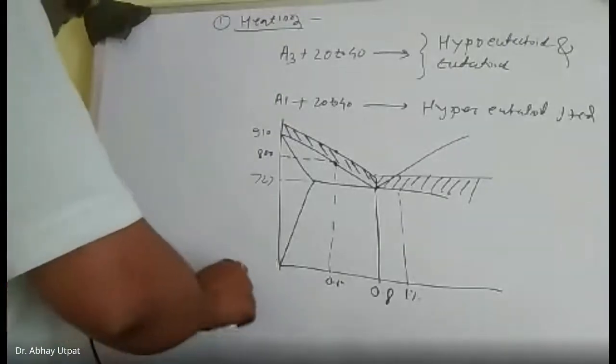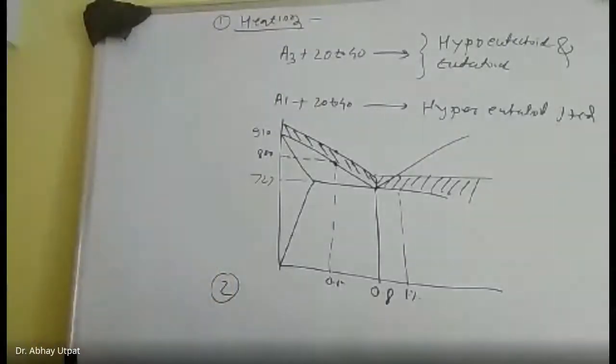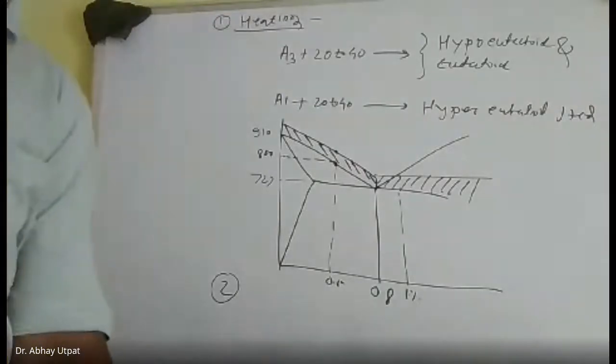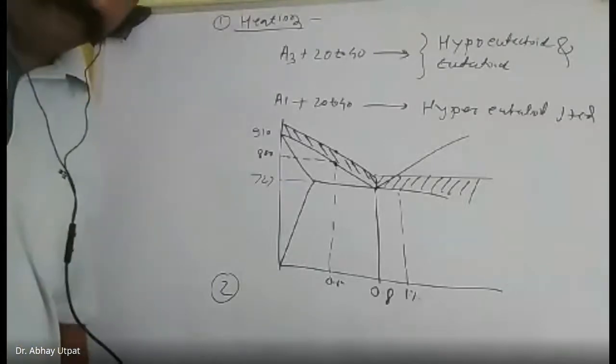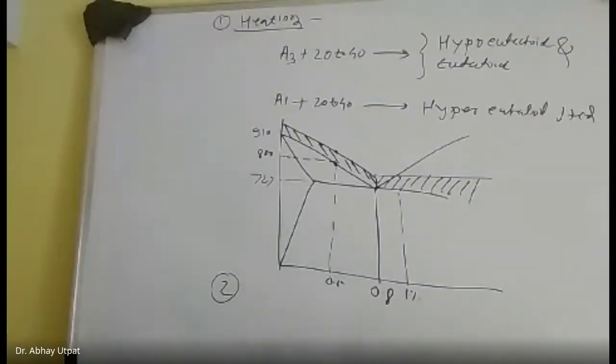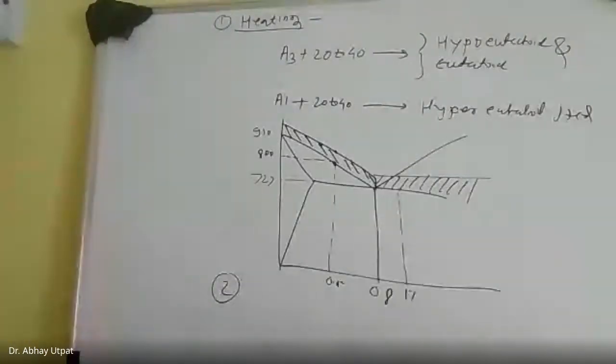Second point, soaking. Soaking means holding. Soaking is carried out at minimum 1 hour for 25 mm section.